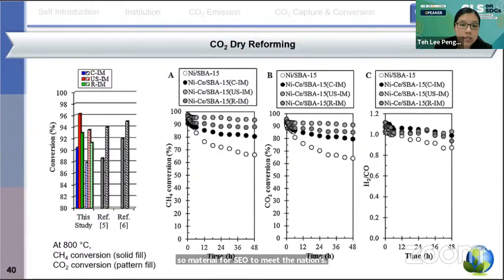We also studied a series of nickel ceria SBA-15 using the conventional impregnation method, the ultrasonic-assisted impregnation method, and the reflux impregnation method. So we compared the different nickel and cerium loading techniques towards the performance of the CO2 reforming of methane.